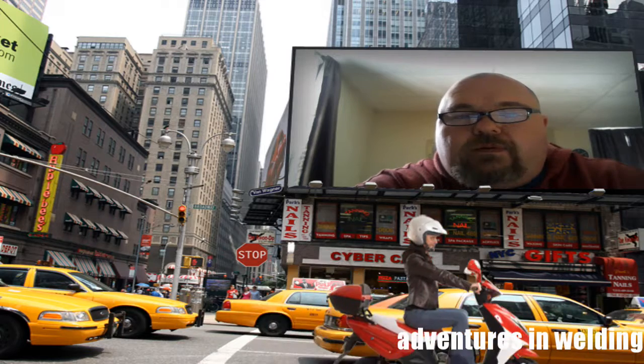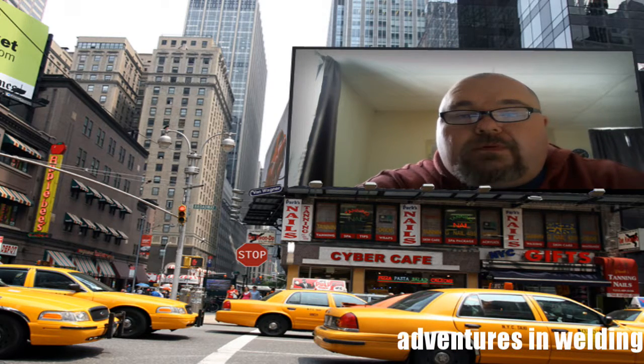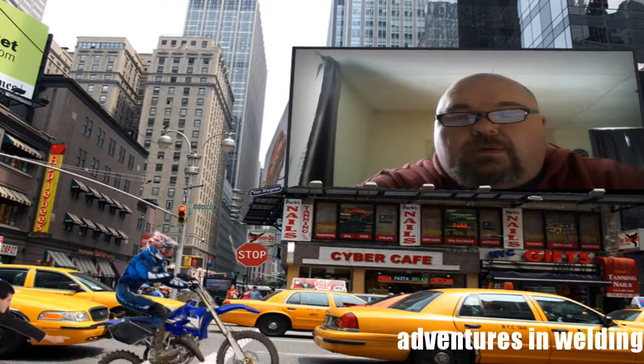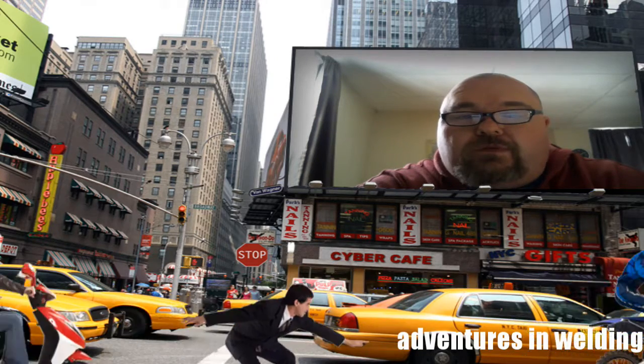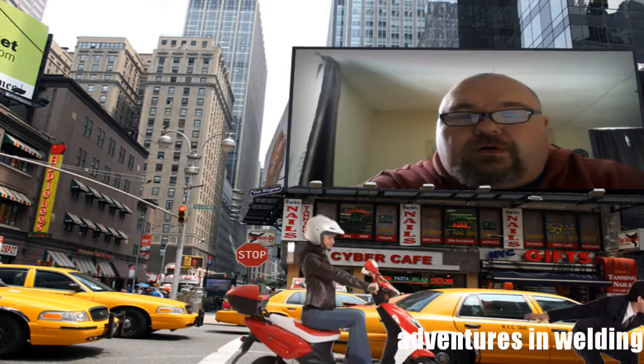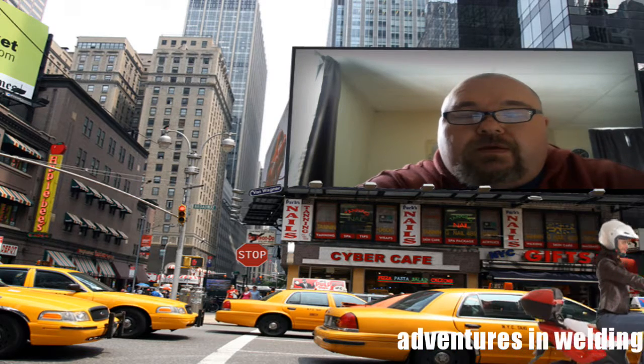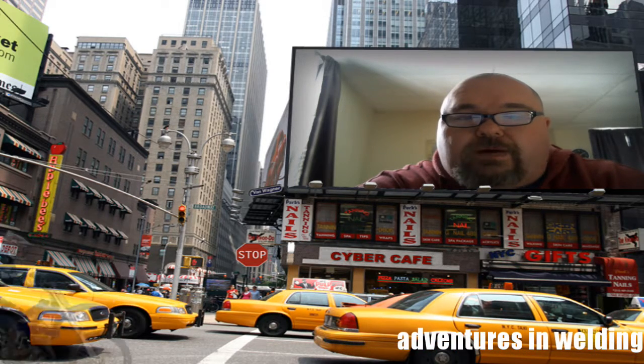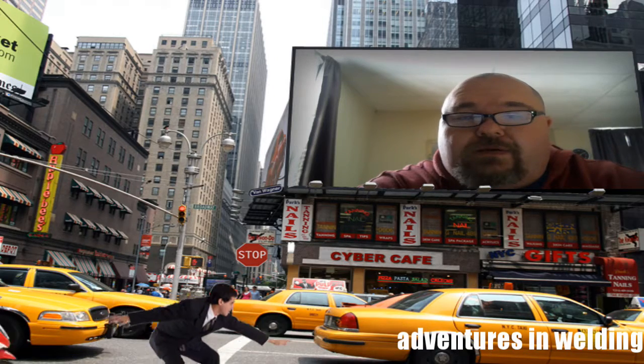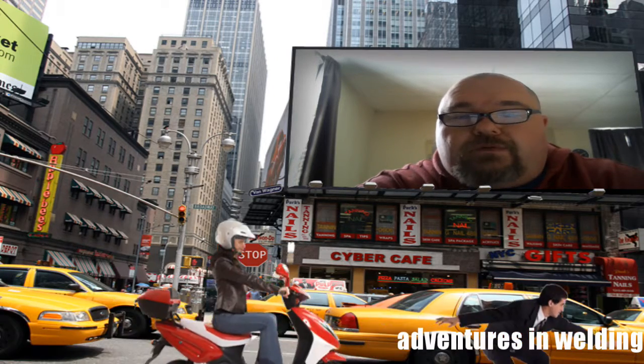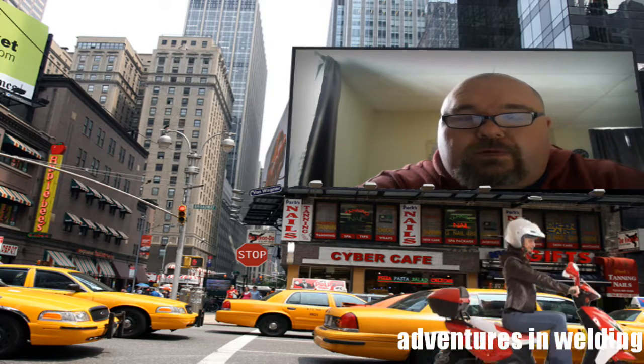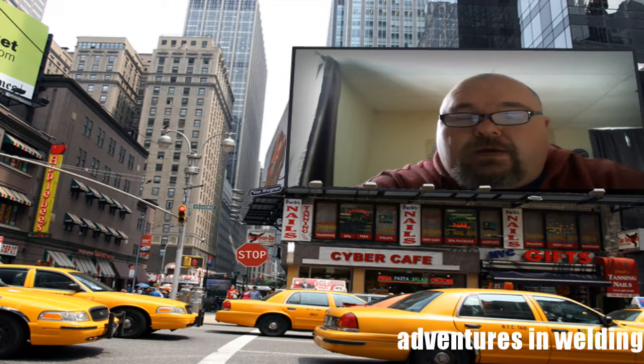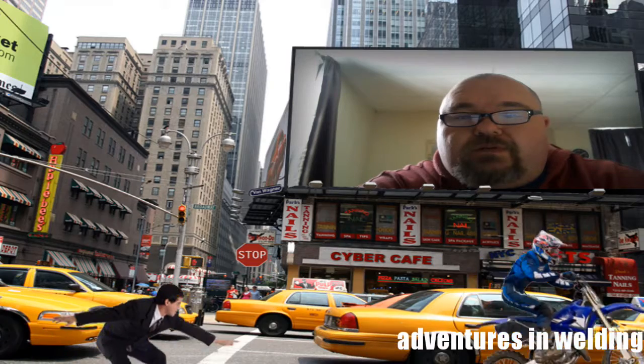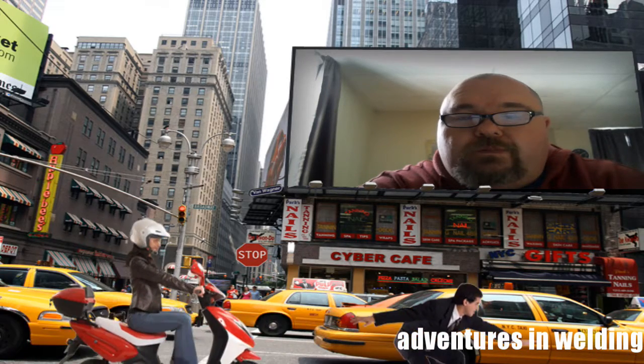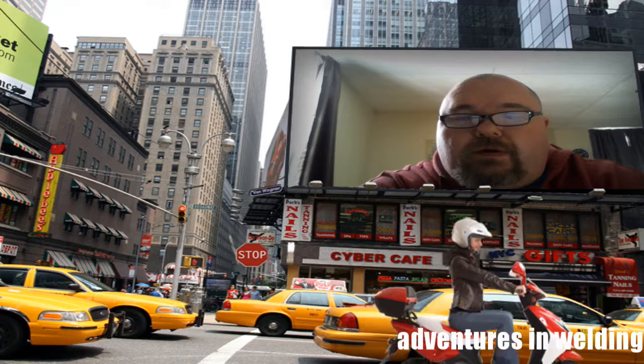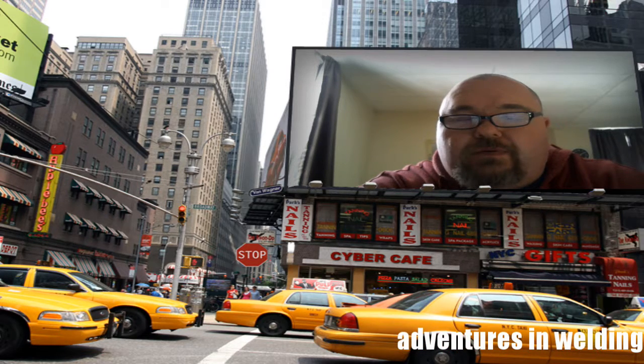And what we're doing is we're causing chromium precipitation. The chromium that gives the stainless steel all of its features, the hardness, the resistance to corrosion, is being sucked out of that joint by the heat. And it's also being sucked out of the heat affected area, causing that portion of the weldment to become brittle and to also become susceptible to the corrosion and the oxidation. So we got to watch our temperatures. That's really all I'm saying.